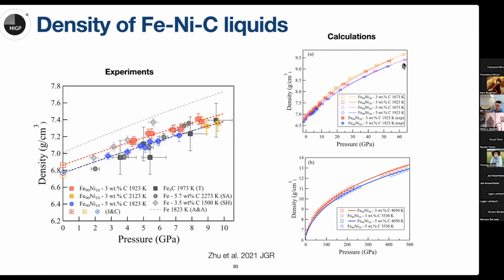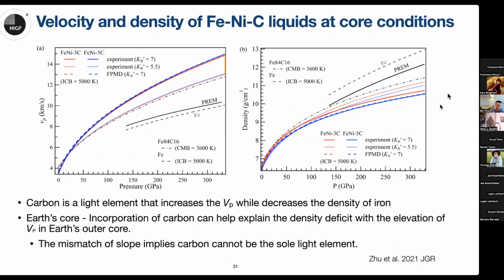In this run, we extrapolate to 60 GPa, and then we also extrapolated to much higher, even higher than the liquid outer core condition. From that, we have a better way of constraining the density of the iron nickel carbon liquid under the Earth's core condition. And our liquid density from our experiment compares pretty well with the calculated result for the density of iron nickel carbon liquid. So this is our result for the equation of state.